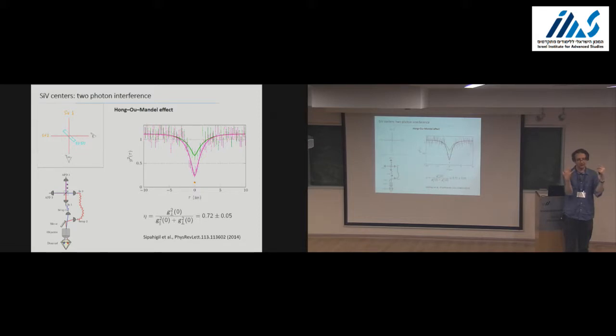So that creates a vibration of the lattice, and that basically leads to absorption with creation of the phonon or emission with the creation of the phonon. And this is a phonon sideband. So those are two different features. The second one is relatively hard to completely suppress. There is still about 30% of emission with creation or emission of the phonons.